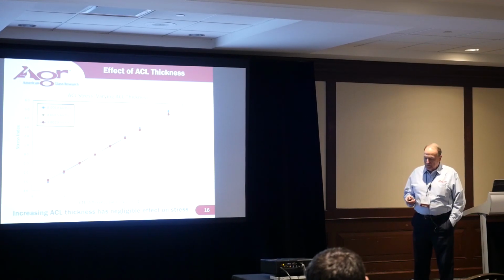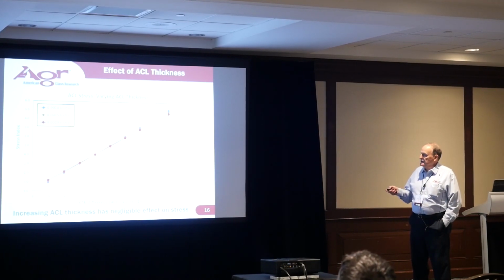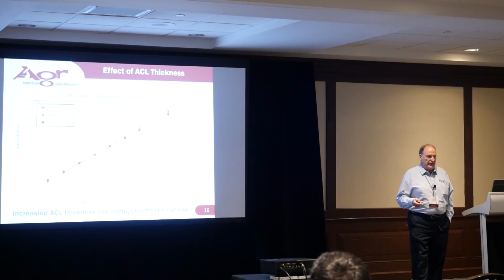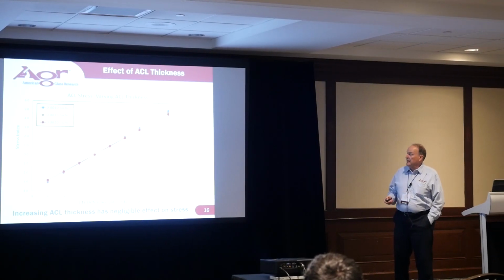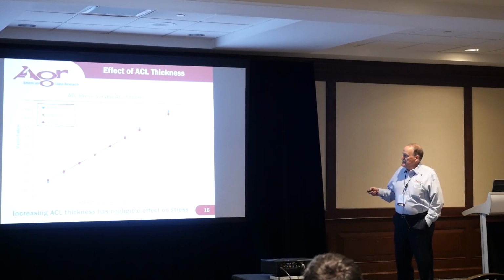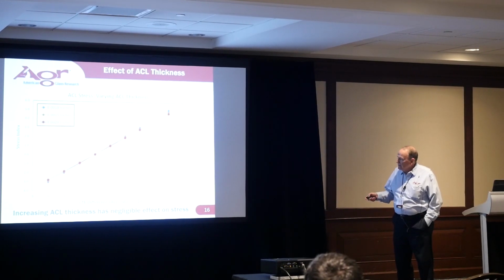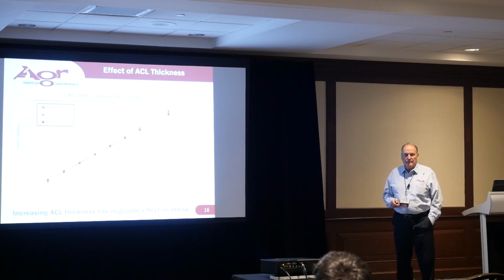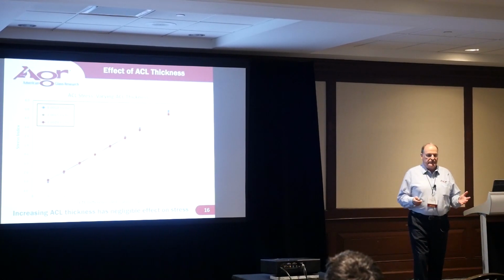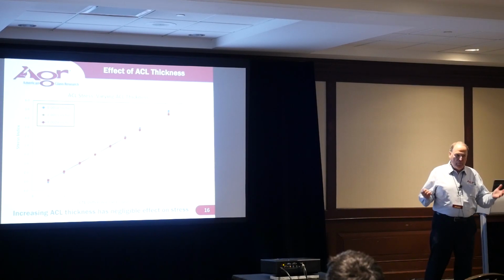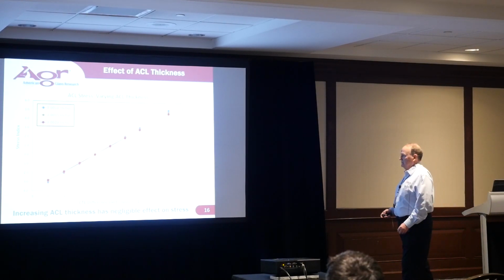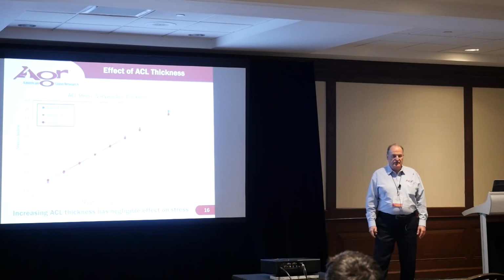Now, the first thing we wanted to look at was the effect of the ACL thickness. Remember, we chose 1, 1.5, and 2 thousandths of an inch. And what we're looking at here is the stress developed in the ACL itself. You can see that the thinner ACL showed a slightly higher tension stress here, and a slightly higher compressive stress down here. But overall, the effect of the ACL thickness is very, very minor. In fact, we said it's negligible. We're not worried about these very slight differences.